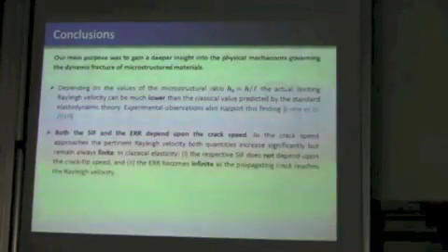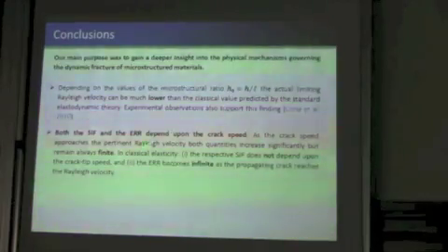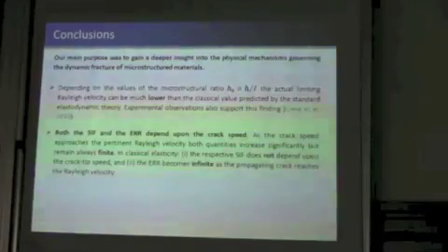We have seen also that both the stress intensity factor and the energy release rate depend upon the crack speed. And as the crack speed approaches the pertinent Rayleigh limit, both quantities increase significantly but always remain finite. Whereas in classical elasticity, the respective stress intensity factor does not depend upon the crack speed, and the energy release rate becomes infinite as we approach the Rayleigh limit.